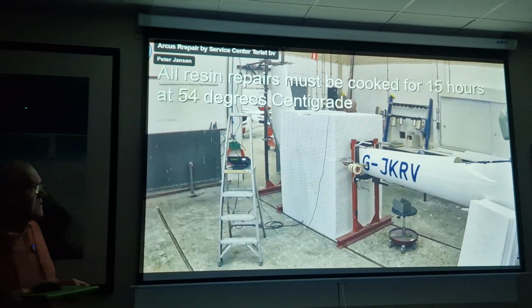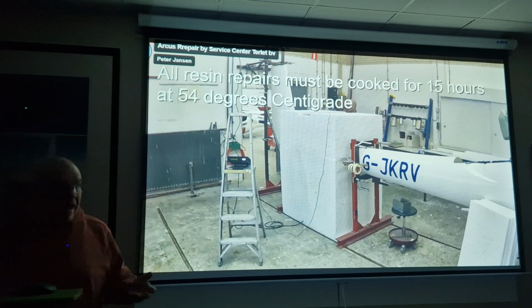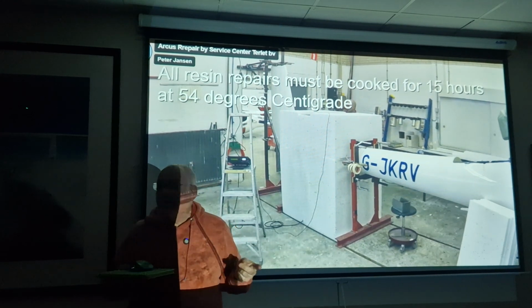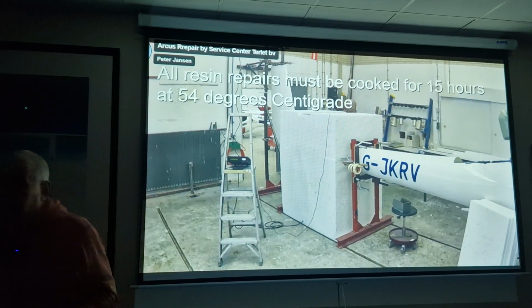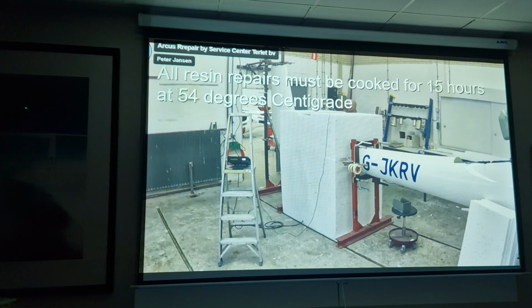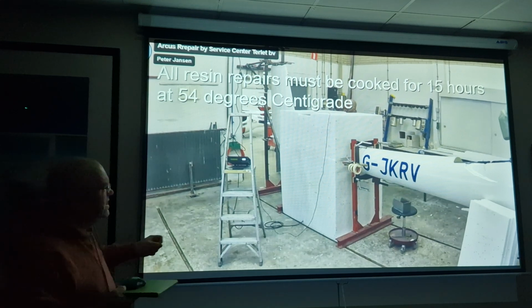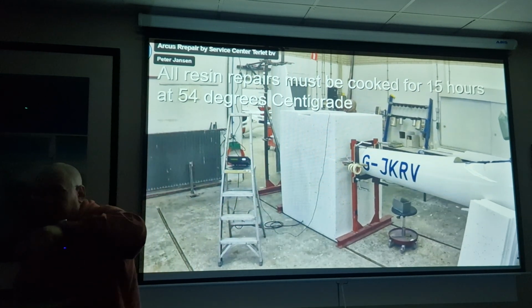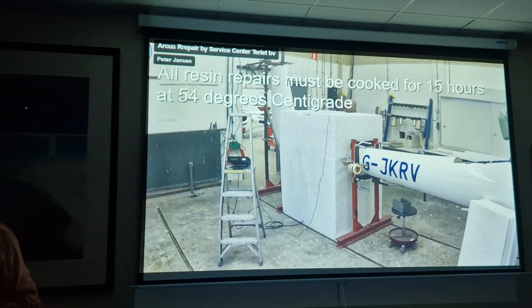And the regulators, the CAA, don't know much about how to do this job, but they do know that in the big airliner world, they have to be post-cured. Post-cured is when you cook it after repair. Boeings are exactly the same, no different, but they're at 160 degrees, that's the difference. So when we do this, we actually have to give them a temperature trace proving we kept it at the right temperature for the prerequisite time. That's now part of the work pack and compliance details.